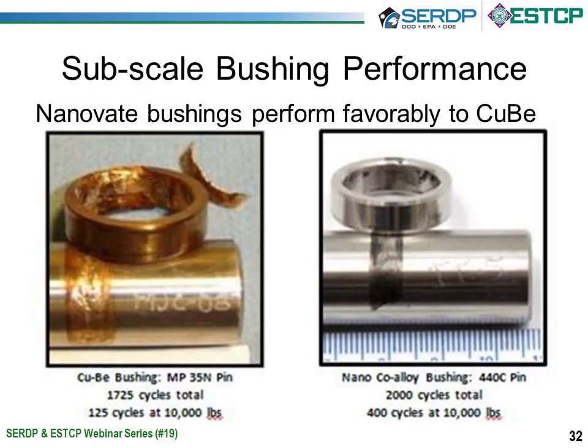So in this case, the copper beryllium bushing only made it to about 1,725 cycles before it started to break away, whereas the cobalt alloy material made it up to a full 2,000 cycles, 400 cycles at the 10,000 pounds, and the material is virtually untouched. If you looked at the material before and after the test, it looked pretty much identical, showing the very good performance.